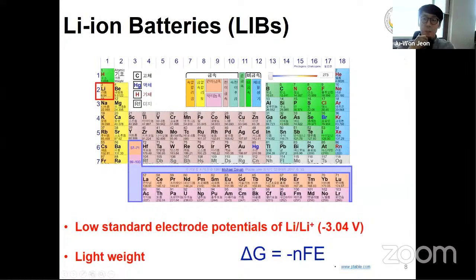So why is the lithium-ion battery the most widely used one? Because it has a low standard electrode potential, around -3 volts. This electrode potential is quite low, which means lithium is easily oxidized, and then we can get a high voltage. And this voltage is directly proportional to the Gibbs free energy change, which means if we have a large voltage, we can obtain high energy.